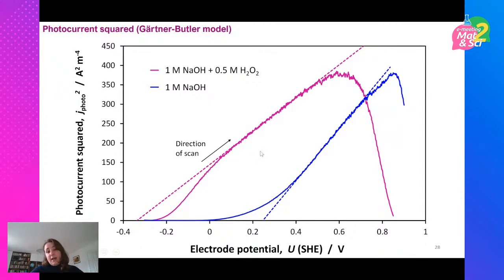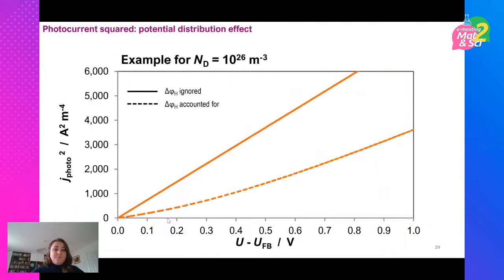And even when you use a scavenger, such as this H2O2, you can see that even there you have a slight S-shaped behavior over small band bending. And these values are completely different. So if you were to just do this using a hole scavenger, is that the true flat band potential? Well, I think the point here is that you really have to use several techniques and they have to agree for there to be any certainty about the flat band potential value.